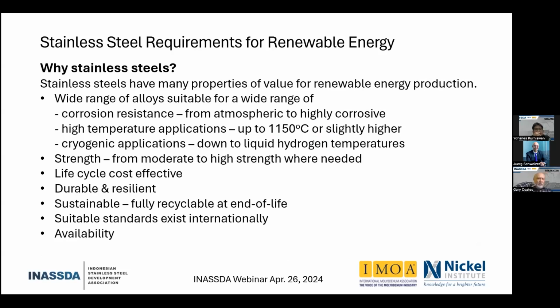So a little bit on why stainless steel. Well, because stainless steels have many properties of value to the renewable energy production area. So first of all, there's a wide range of alloys suitable for a wide range of corrosion resistance, from applications, maybe structural, that are resistant to atmospheric corrosion, to some very highly corrosive alloys for highly corrosive conditions. High temperatures. We can go up to about 1150 degrees C or slightly higher with certain stainless steels. And we can go down to very low temperatures, liquid hydrogen temperatures, maybe even liquid helium temperatures if we had to with certain of the stainless steels.